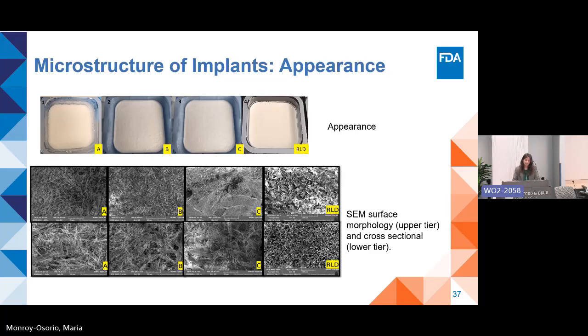Then we investigated this collagen implant to obtain the morphological information by using scanning electron microscopy. We found that the implant shows distinct pores with irregular organization of the fibrillar structure, and here the upper tier shows the top surface of the implant, and the lower tier shows the cross-section area of the implant. The main point is that this implant doesn't show any similarity compared to the RLD, where RLD shows the honeycomb-like structure.